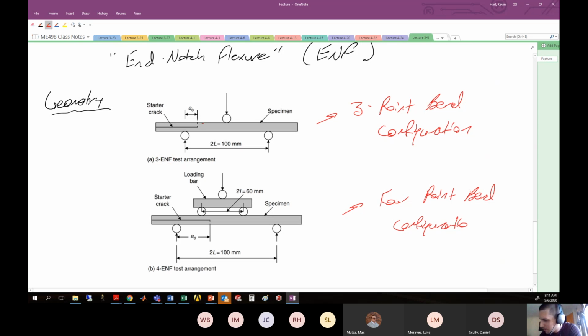All right, so here we put our starter crack on the edge of the sample and move its way in, right? That's the general idea. Both of these samples have the same general idea: you have the starter crack that starts at the end of the sample and moves its way in. So the samples look basically exactly the same as the double cantilever beam specimen. You've got the starter crack, which is initiating from one of the thin edges and moving its way in.